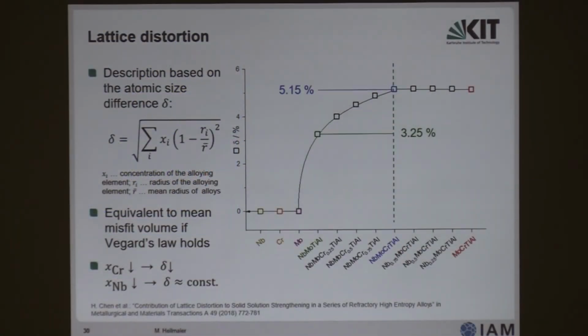Okay, and then just to give you a flavor of what we did, I don't want to go through the whole analysis. The atomic size difference is the measure for the lattice distortion. So a high lattice distortion means I have atoms of largely different sizes in my solid solution. The lattice distortion is proportional to the atomic size differences, and this can be simply calculated by this formula. Here is the average radius of the alloying element, and here is the mean radius for all the alloying elements in the alloy. This is simply summed up and then the square root taken. And what you see here, of course, is no lattice distortion in the pure elements, so this is 0. But then the lattice distortion goes up quite a bit, up to 5%. 5% is a huge lattice distortion for a solid solution strengthened alloy. Imagine, for example, brass, copper, zinc, much lower, or aluminum, copper, much lower.